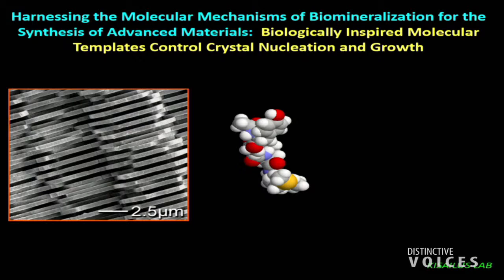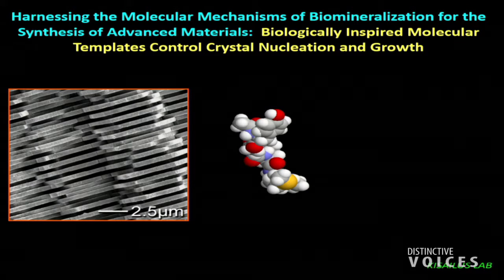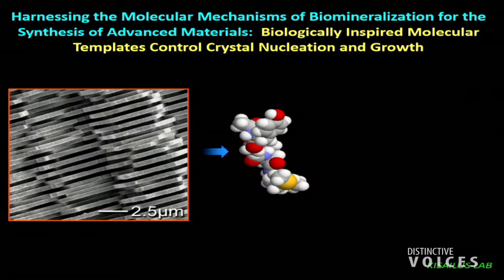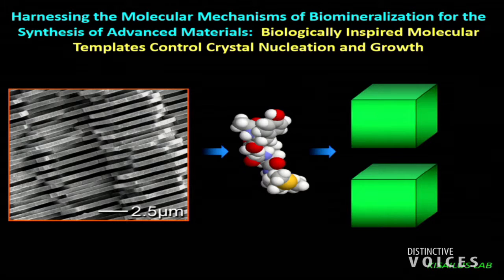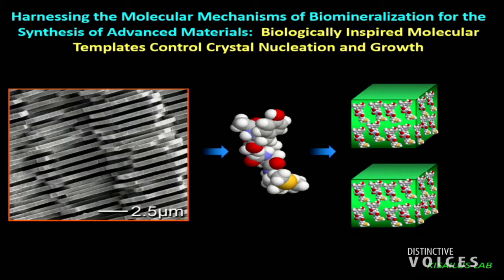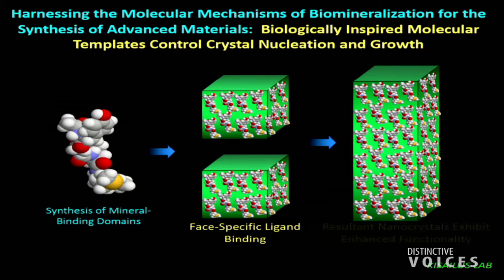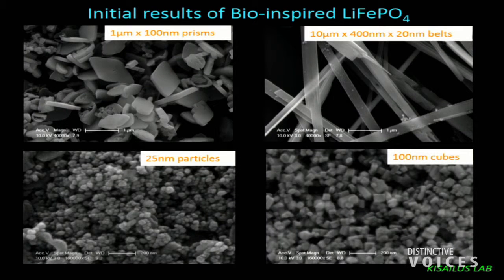So in our lab, we use bio-inspiration. We say, here's the shell. The shell has controlled growth by using organics. So here's a little organic molecule, and it uses this to guide growth, or could we use something like this to guide the growth of these battery materials? So we take these organics, and during the growth of our crystals for the batteries, we hope that these organics will bind to these structures and control their growth to give us something that might look like this. And so this is all I wanted to show.